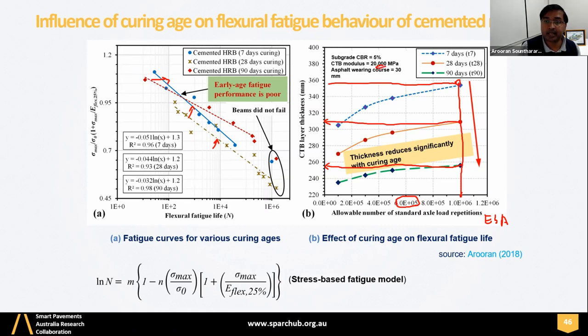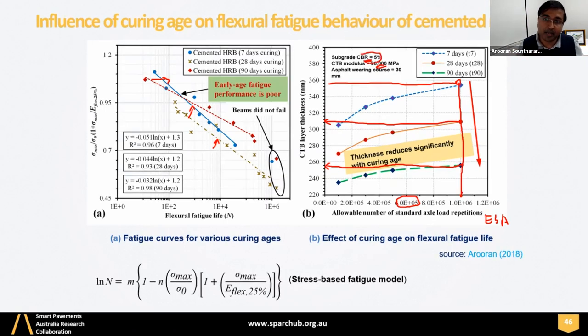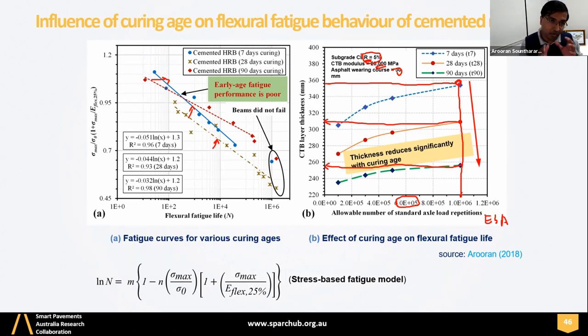Remember the modulus and the subgrade, because cementitious material is not the only layer in the pavement. There are other layers as well, subgrade as well as asphalt bearing course. You need to take that into account as well. So assuming that your subgrade is 5% and your bearing course is 30 millimeter, if somebody wants to construct a CTB layer and they want to urgently open, what happens is it doesn't gain the strength. Therefore, it requires certain time to cure. But if you want to open it, you want to prevent the failure. You don't want the pavement to fail just after 7 days. So you need to provide enough thickness such that your pavement, even under lower strength, sustains the required traffic.